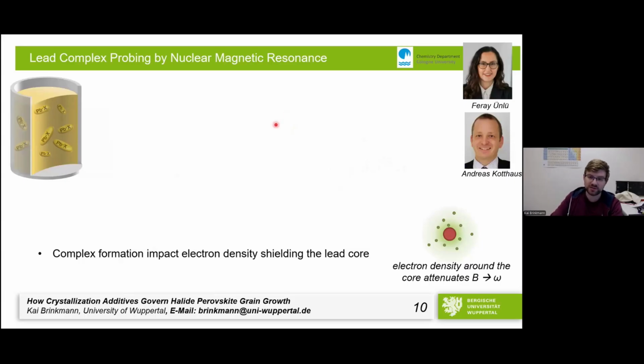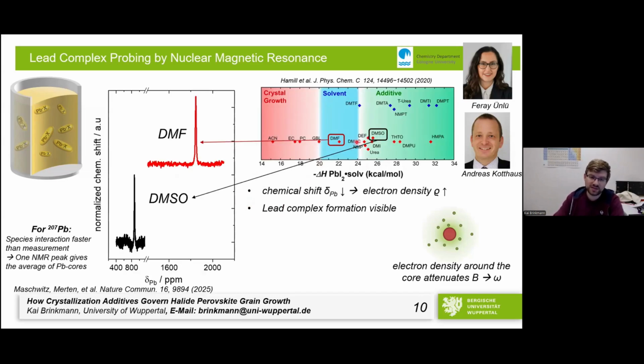Another way of probing this is having a look at the lead chemistry. So what we did here is we used lead NMR, basically liquid NMR on the lead core. Here you can see the ability of the solvent to coordinate with the lead. This is a paper from Kai, quite a while ago already, where he was classifying different solvents or materials as solvents or additives by their level of Lewis basicity, which basically means that they interact with the lead core. We were able to see this quite nicely with the lead NMR.